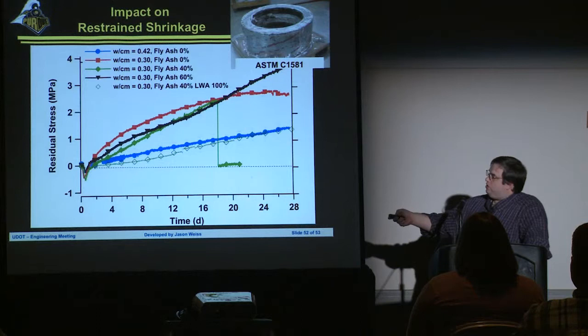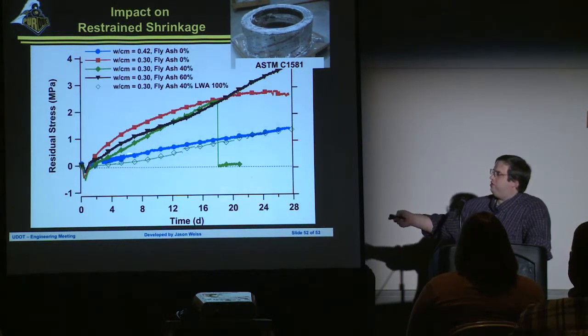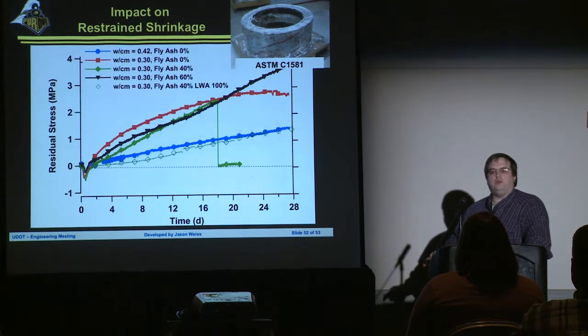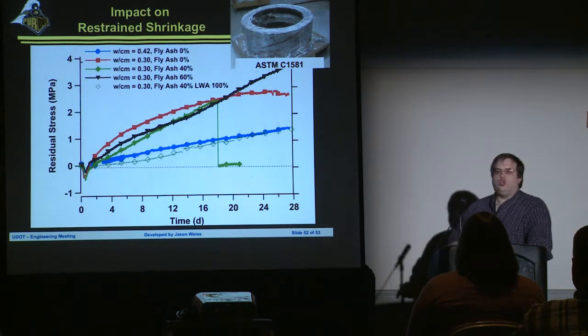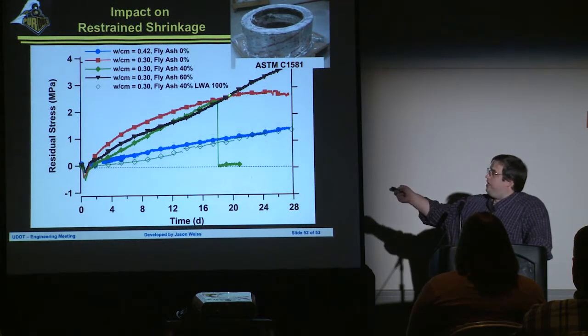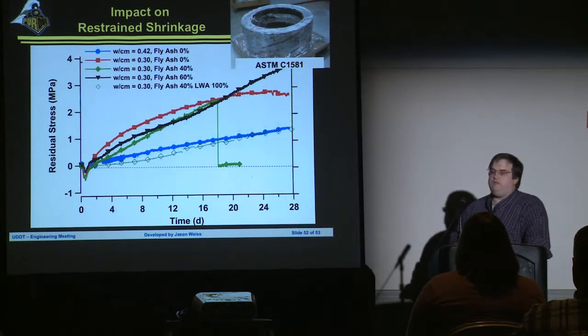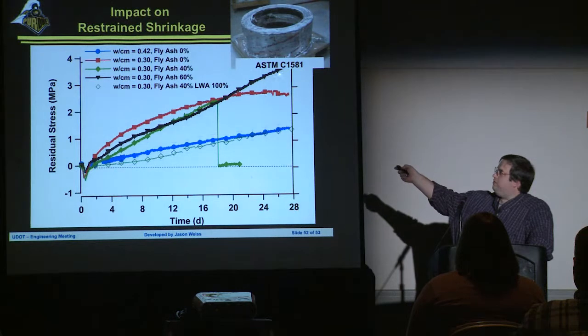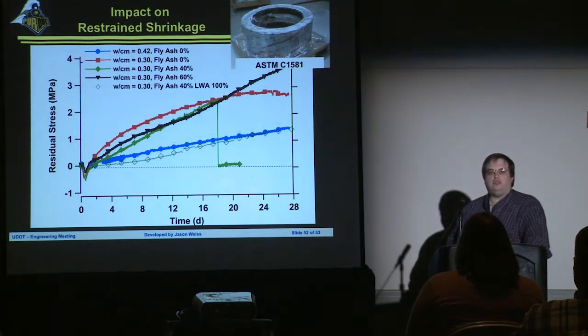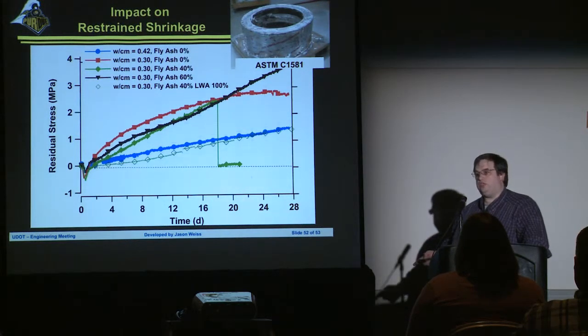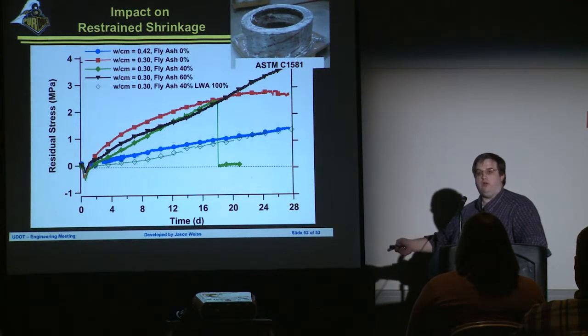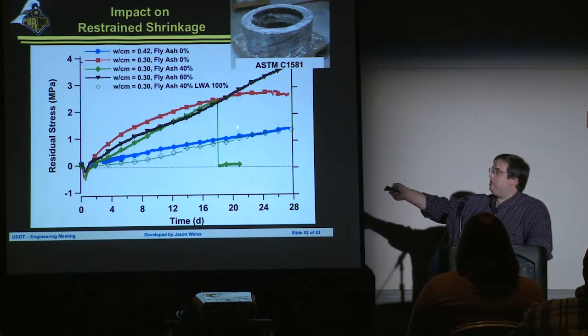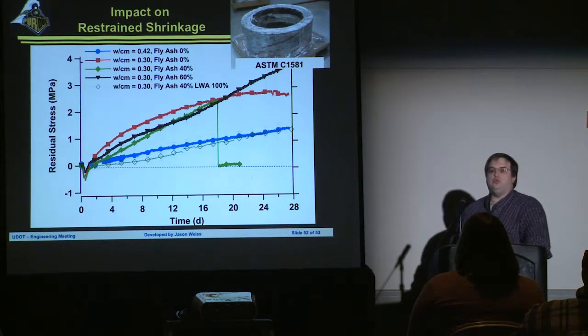All right, but what I'll start to do here is I'll start to say this blue line is our conventional bridge deck mix. If we lower the water to cement ratio, we drop it to a 0.3, we see the stresses go way up in the restrained shrinkage test. If we now start to replace 40% or 60% fly ash, we can see our 60% fly ash system cracks. Our 40% fly ash system has a very interesting behavior here. The stress continues to go up and up and up over time. This is because fly ash has more chemical shrinkage and it takes place longer because it's hydrating for a longer period of time. If we take these mixes and we use internal curing, we drop those stresses right back down to what we saw in a 0.42 water to cement ratio.